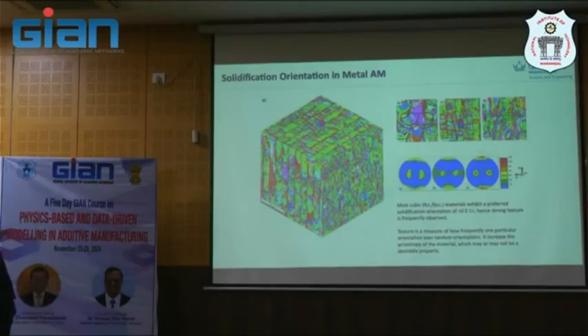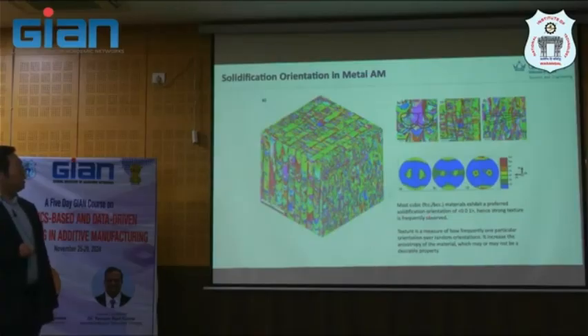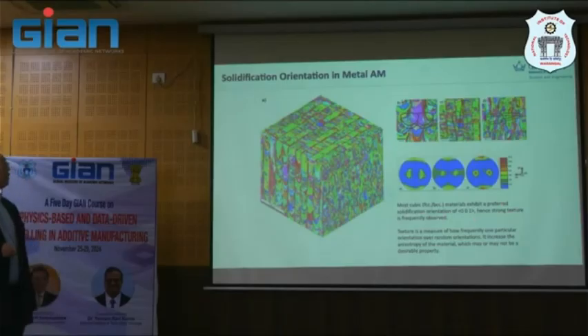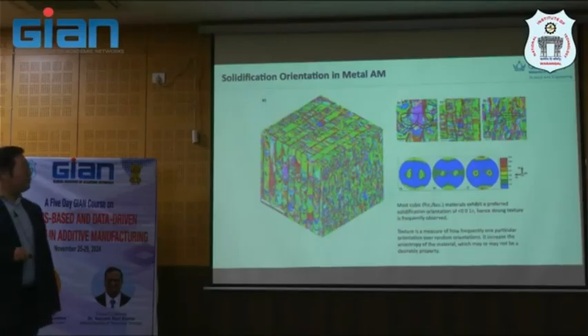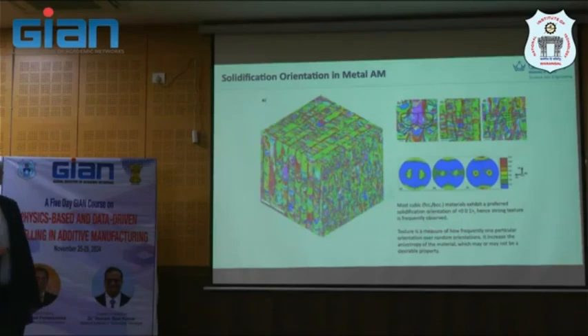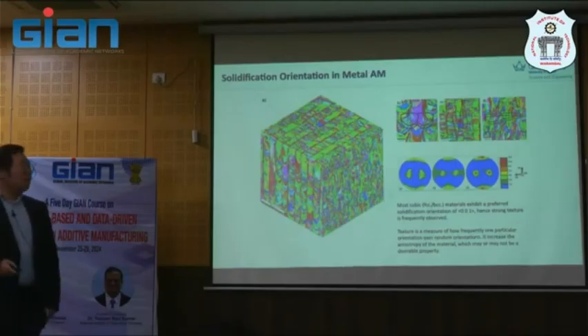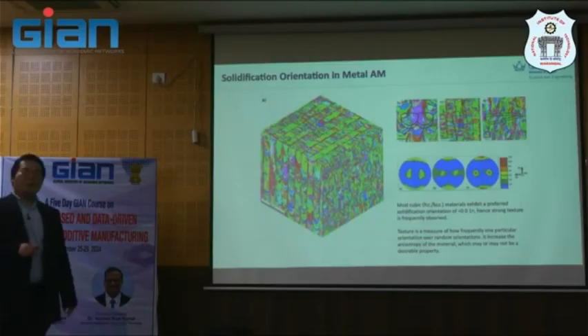And then this is related as well to the process. You see with different melt pool shape here that this paper tries to relate very well that most cubic material preferred orientation is 001. And this is a strong texture direction. But this texture we call tailoring. We call it texture control in additive as well. Yeah, we need to control this texture to align with what we want, because the property will follow that.